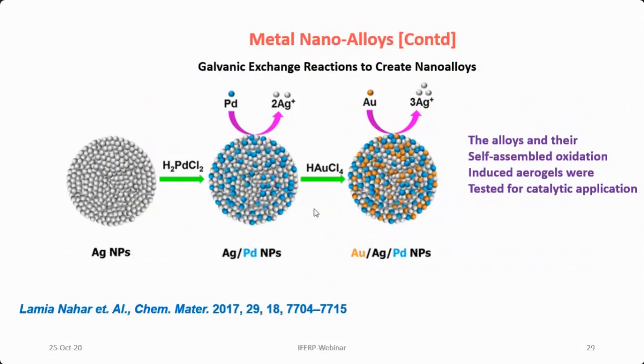So this was the kind of alloy. Again, they put a gold precursor, and the gold has also been reduced to gold 0, and silver got replaced after oxidation. So the cluster they ended up with contained gold, silver and palladium nanoparticles, and they used this for various applications. One of the applications was catalytic applications.